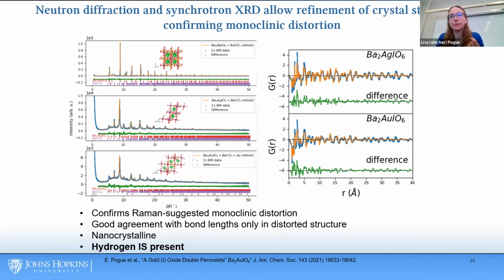So yes, the peaks are broadened because the crystallites were very small. I was able to do the refinement because the peaks are still reasonably sharp. And by combining both the neutron PDF data and the X-ray diffraction data, I was able to find a consistent set of coordinates for the given symmetry that explain both. It is likely in the structure that there are still some deviations from that, and especially because the peaks are broad, there is some disorder there, but it does seem like what we found was very representative of the structure as a whole. The specific sites that were moving during those refinements tended to be the oxygen sites.